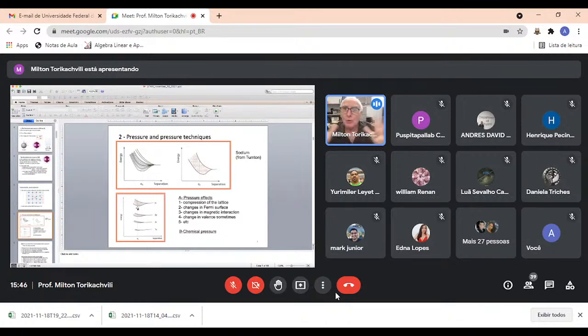So if there are magnetic interactions, either direct exchange or indirect exchange, since those ion cores are slightly closer together, there's going to be a change in the magnetic interactions. Also, sometimes, particularly when you look at the rare earth elements, the valence is somewhat unstable. So by applying pressure, you may be changing the valence slightly.